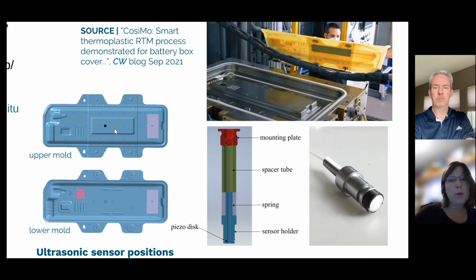The sensors that mostly were used out of a network of 70, most of them were these ultrasonic sensors. And these were developed by the University of Augsburg. And I'll be doing a blog on that pretty soon. And what I thought was interesting is that I had never heard of ultrasonic sensors, but Marcus Saus at the University of Augsburg was telling me that these are really common. They're used in industry all the time. The problem is that the ones that are commercially available max out at about 150 degrees C. And what they needed for this process was a little bit higher because of the thermoplastic. So they were looking to take it up, I believe, to 300 degrees C. And so they just redesigned an ultrasonic sensor to where it would work for their process.